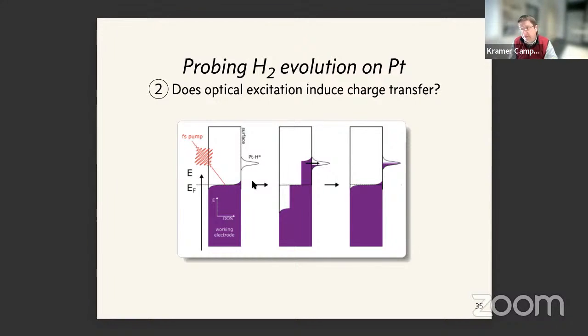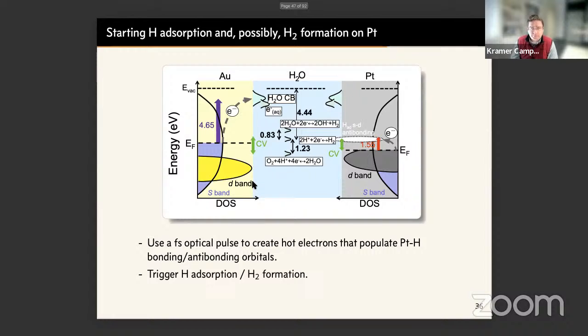So the first thing that we wanted to demonstrate is that if this is true, perhaps this optical excitation would induce charge transfer that we could detect electrochemically. So once again, this is the same cartoon that I've shown you before. Now we're looking at the right side of the diagram. And we have now bonding and antibonding states within the range over which water is thermodynamically stable. And so we use a 1.55 eV photon energy pulse. It's bigger than the water window, so it should be more than sufficient to try to populate this antibonding state, and with the hope of triggering hydrogen adsorption, desorption, and H2 formation.